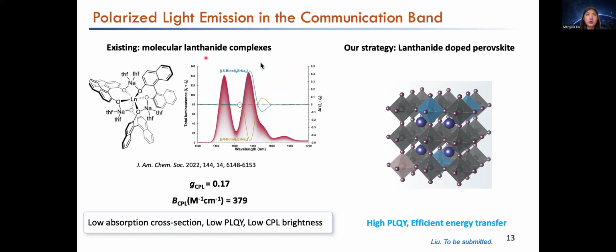So we look at the existing materials that can generate polarized, especially circularly polarized light in the infrared, and the only existing one is the molecular lanthanide complex. This is a material with a lanthanide ion sitting within a distorted chiral molecular complex. This chiral molecular complex can absorb light and transfer the energy from the organic into the lanthanide center, and the lanthanide will emit light. And because of this distorted environment, the lanthanide will have their rotational strengths opened by the chiral geometry. This will result in a circularly polarized light emission.